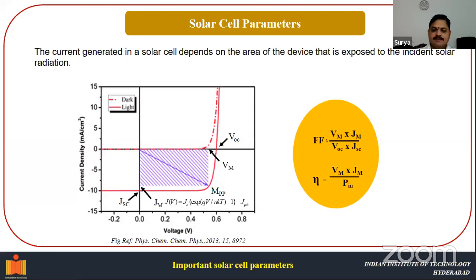Okay, so based on these parameters, we can define important solar cell parameters like the fill factor and the efficiency of the solar cell. The fill factor is defined as Vm, the maximum voltage, multiplied with the maximum current density, divided by the open circuit voltage multiplied with the short circuit current density. This actually gives the fill factor. So this signifies how square your IV characteristics are. Whereas the efficiency you can define as Vm multiplied with Jm divided by Pin. So this is how one can define the fill factor and the efficiency.